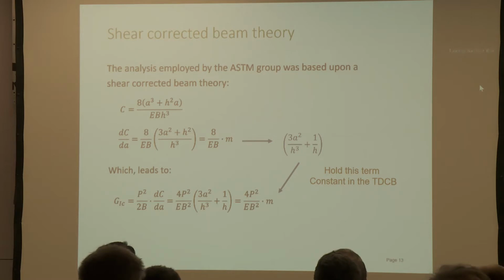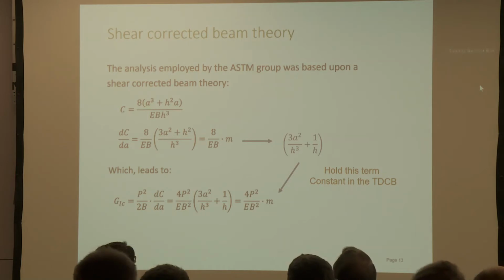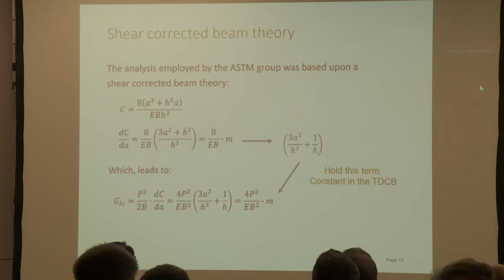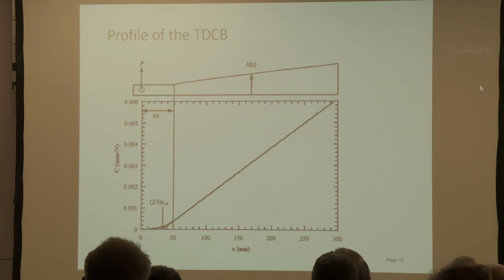Now, a rather nice design was to recognize the term in blue brackets here could be held constant to simplify the analysis. And that could be achieved, for example, by height tapering the beam, which led to the tapered double cantilever beam that we saw on the last slide. The tapered double cantilever beam will be designed with a constant value of m. Of course, the actual geometry will vary as m changes, but typically you can use a value of m to hold the rate of change of compliance constant. And of course, there are great advantages for doing that.